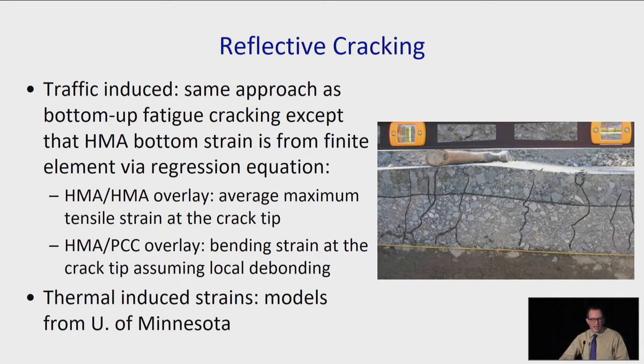For reflective cracking, we're using the same approach as the bottom-up fatigue cracking, except that the HMA bottom strain is from the finite element via regression equations. For HMA on HMA, we're using the average maximum tensile strain at the crack tip. And for HMA on PCC, it's the bending strain at the crack tip, assuming local debonding of about 100 millimeters on each side of the crack, which comes from our colleagues at Tongji. And we're using thermally induced strains using models from the University of Minnesota.